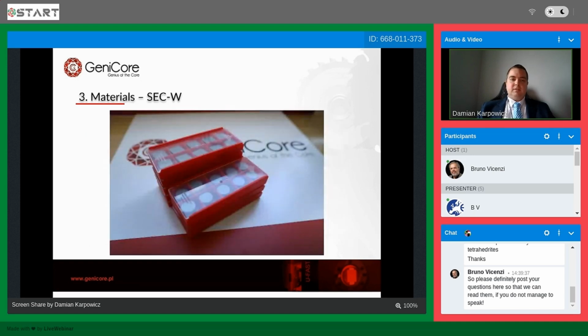And as mentioned before, 65 pieces per one run. So it needs to be emphasized that we are able to achieve better results when it comes to mold designing. And this is just a picture to show you the final product. Of course, to achieve such a shiny effect, let's say, for the cutting insert, it is also machined after the process. Nevertheless, we produce it in near net shape, which limits the machining to the very minimum.